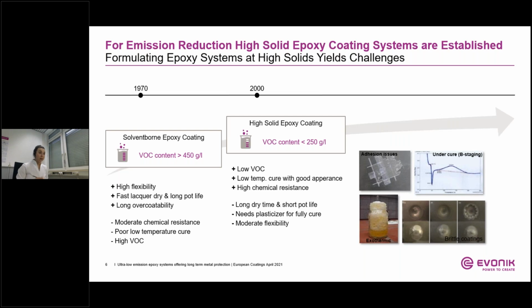But we have to keep in mind that the handling and the performance characteristics of high solids are different than solvent-borne epoxy coatings. There is a negative impact on the pot life, coupled with an extension of dry time versus solvent-borne systems. In the case of high solids, the polymeric network has to react and build sufficient molecular weight to reach the gel point, or in other words, dry to touch state, whereas solvent-borne systems are already high molecular weight polymers and dry to touch or lacquer dry as soon as the solvents evaporate from the coating film.